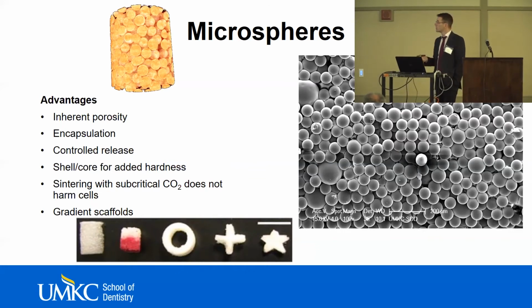Also, when you use shell core materials like different polymers on the outside and inside, you can tweak the mechanical properties of the scaffold you're trying to make. And sintering with subcritical CO2 has shown not to harm any cells that were either encapsulated in the microspheres or were seeded onto the scaffold before sintering. By filling molds with two different types of microspheres, you can also create gradient scaffolds when you change the ratio of your two materials, as you can see here in the red and white scaffold.